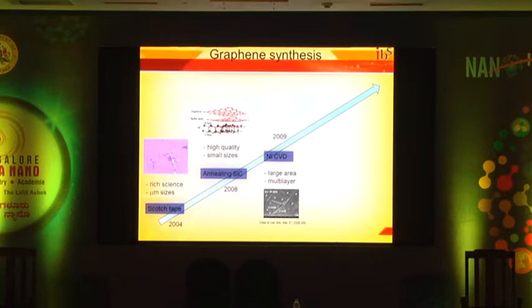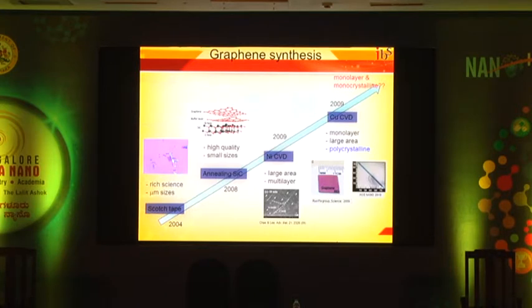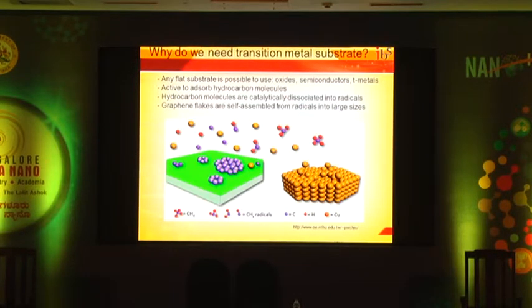So people started working with some metal. Of course, this metal is a catalytic substrate, and if you supply hydrocarbon gases, you can simply crack them due to this catalytic effect, and then we can form some layers of graphene in a large area. But when people used nickel, because of the high carbon solubility in nickel, it wasn't easy to control a single layer, and then people came up with the idea of copper, which has very low carbon solubility. And luckily, we are able to grow a single layer very nicely. But still, sheet resistance or mobility is not as high as theoretically expected. So people wondered what's going on. One reason, of course, is that this is not a single crystal, it's polycrystalline. So people try to synthesize monocrystalline or single crystalline graphene. This is what we've been focusing on.